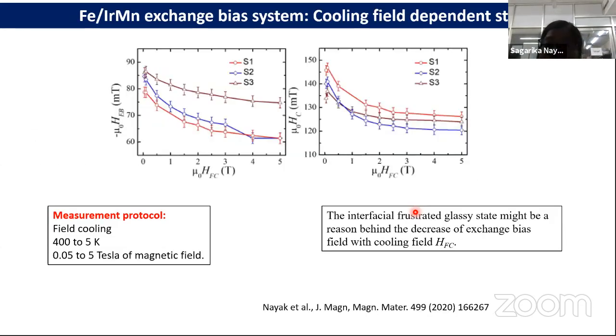Next, we also perform field cooling dependent study to see if this frustration has any role on the exchange bias field or not. So this is all the same measurement protocol. We field cool the sample from 400 Kelvin to 5 Kelvin, and varied the cooling field from 0.05 Tesla to 5 Tesla, and found that the exchange bias field is actually decreasing with cooling field, indicating that the interface is not just like a ferromagnetic and antiferromagnetic interface, because in a ferromagnetic and antiferromagnetic interface, the exchange bias field should increase with cooling field, because with the increase in cooling field, the pinning moments increase and it increases the exchange bias field. But because of the presence of frustrated interface, we found the decrease of exchange bias field with cooling field. Also, we found the decrease in coercive field with cooling field.